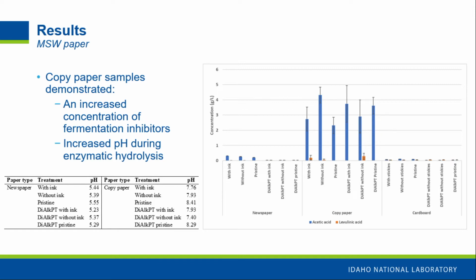Another thing we noticed was that we had an increased pH during enzymatic hydrolysis. And so the enzymes that we're using have a very narrow range that they work in, between 5 and 5.5. If you look at this chart on the bottom here, on the left we show newspaper, and our newspaper samples fall within that narrow pH range we need for our enzymes. But if you look over at the copy paper, they're really high pH. And so we think that this could really impact the yields that we're getting. Specifically, if you were bringing in a stream that had a high percentage of copy paper, this could really cause you problems if you're trying to do enzymatic hydrolysis and fermentation.